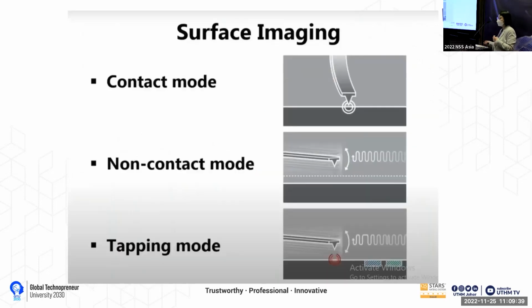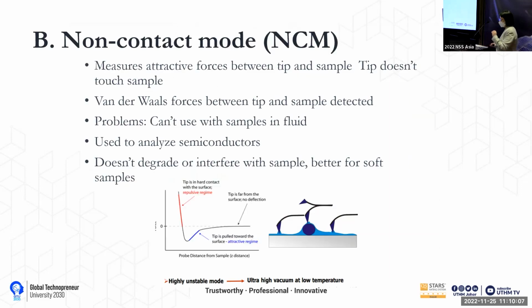Okay, so we have three different types of mode. I think most of you know them: contact, non-contact, and tapping mode. In contact mode, the tip is subjected to abrasion or damage easily because it contacts the sample. So that's why we have the non-contact mode that oscillates over the sample. Or if you have a sample that has strong electrostatic charges, then you're advised to use the tapping mode. So I'll focus on non-contact mode that measures the van der Waals force difference between the tip and the sample.